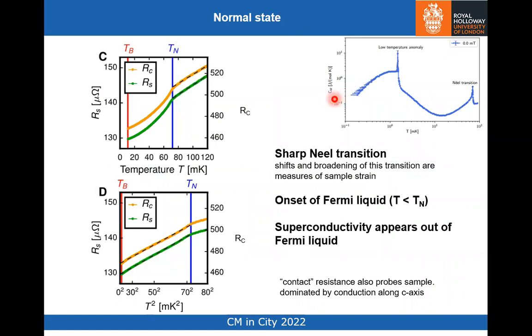So in the normal state then, here's the heat capacity measurement. So there's the Néel transition. Above the Néel transition, we have this linear temperature dependence of the resistance, so-called strange metal behavior. And then at T_N, to very good precision, we go from linear to quadratic. That means then clearly that a Fermi liquid state is formed at T less than T_N.